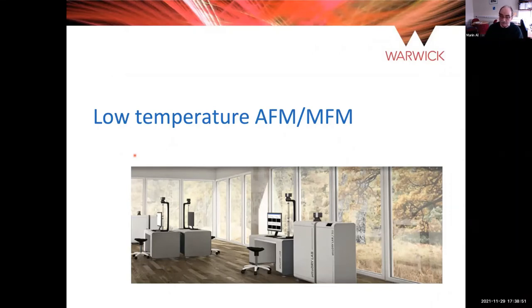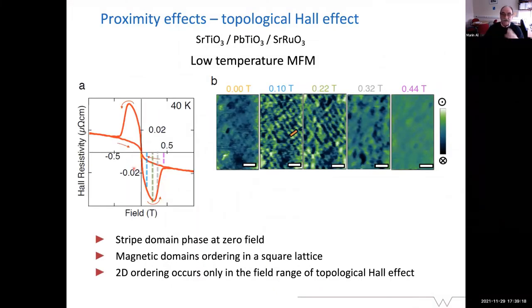And we took our samples and plugged them in, and then we started looking with magnetic force microscopy to detect what would actually be the domain pattern which may be associated with this topological Hall effect, or with the rise in this range of magnetic fields which are exactly the topological Hall range. And we did this. Sam put in a lot of effort and made the MFM work at very, very low temperatures, not only MFM, and then very carefully started measuring. And then you see here that we went in magnetic field exactly in this range where the topological Hall effect occurs.